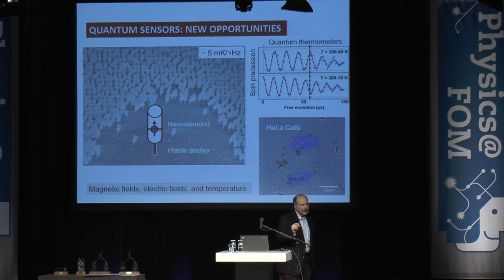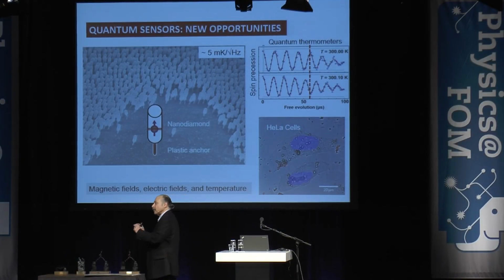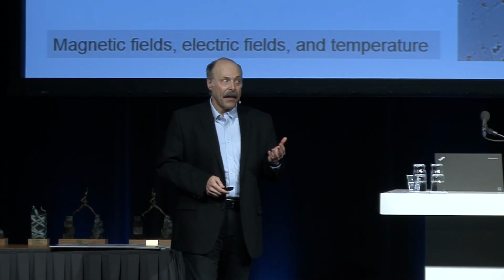And when we talk to some of our colleagues in the world of bioengineering, they're teaching us a lot right now. And one of the things they've been pointing out to us in a lot of biological processes, and I'm barely speaking to the edge of my knowledge here, it's very important to be able to do a precise temperature measurement at a very specific location, say on both sides of a cell wall, where a lot of processes are believed to be driven thermodynamically, maybe not with chemical potentials. And it's been very difficult to do very good local nanometer-scale thermometry. So by functionalizing these outside of the diamond and allowing them to stick in certain positions, there's an opportunity now to do very localized nanometer-scale thermometry based on the quantum state of a particle. I think a type of probe that, again, a few years ago would never have occurred to any of us to use quantum states as thermometers. But now there are a number of emerging applications where nanometer-scale thermometry, in principle, could play a very important role.